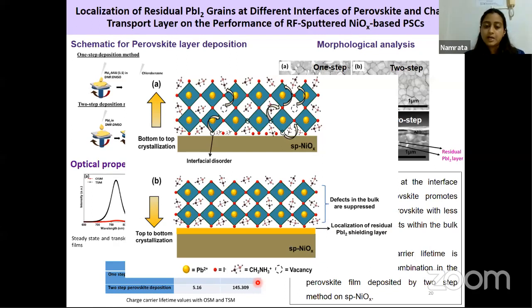the crystallinity is better. This implies that the surface of the sputtered nickel oxide has some defects, and if we directly crystallize the perovskite on top of that, these defects lead to defects in the bulk, and these defects lower the performance of the perovskite solar cells. And these defects are the reason why we are observing the PbI2 at the top of the perovskite, which is further causing voids in between the ETL and perovskite, thus leading to reduced performance.